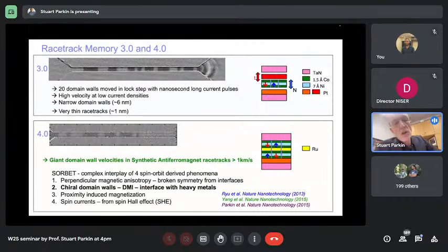Until recently, we were largely looking at racetracks, the horizontal, and we can detect the domains by optical means. We just shine a light onto a racetrack. The light is polarized in a planar direction, and the plane of polarization is rotated clockwise or anti-clockwise, depending upon the direction of magnetization. On the right-hand side, you can see the type of structure here. This structure consists of these green and blue layers. The green layers are cobalt layers. They're 1.5 angstroms thick. The nickel layers, 7 angstroms thick. And the important point is these interfaces give rise to very strong perpendicular magnetic anisotropy. And then you can see underneath we have some orange or red layers which are formed from platinum or some other material which converts charge to spin very efficiently.